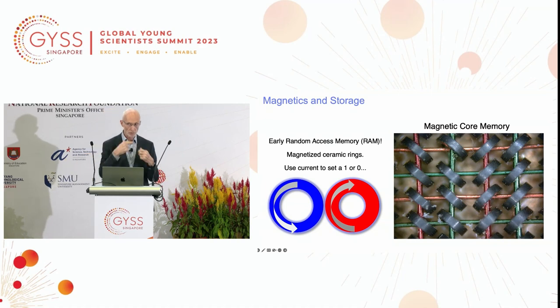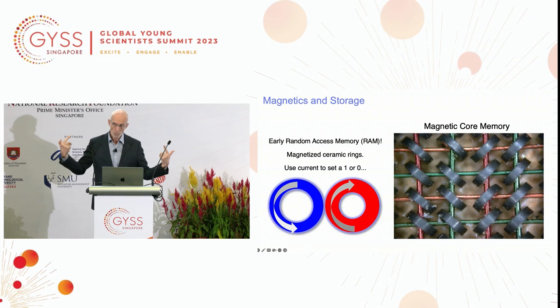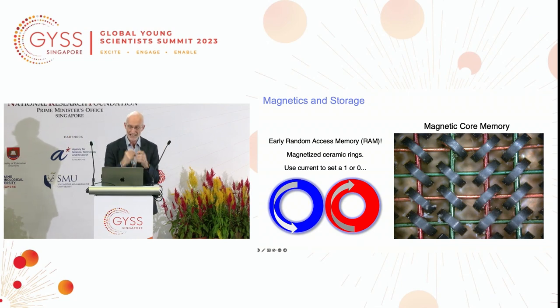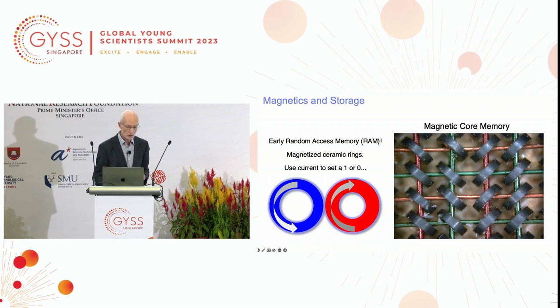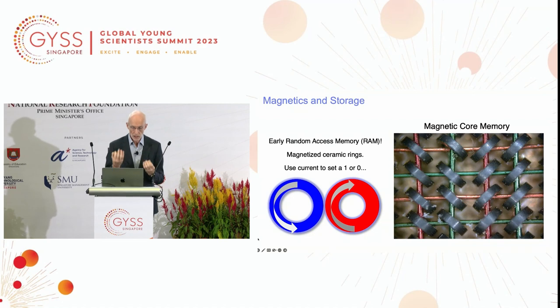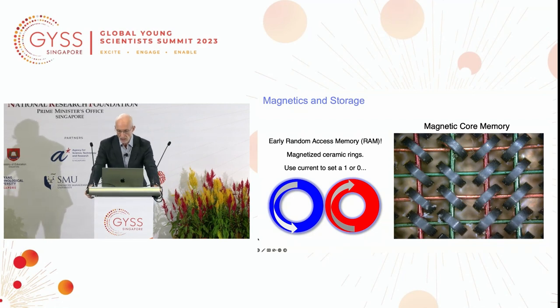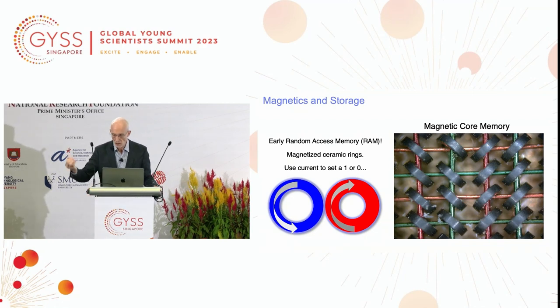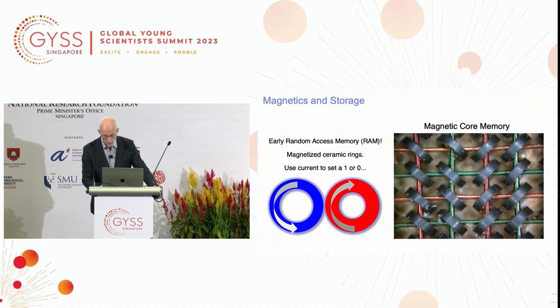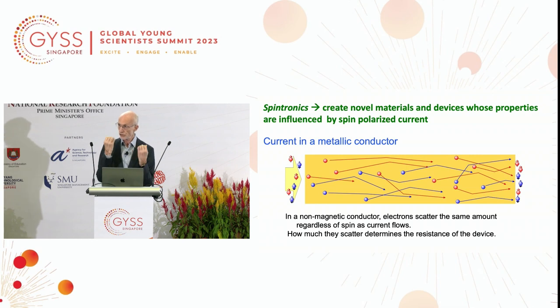If you pass a current through the wire, it will generate a self-amperian magnetic field, and the combination of two fields from two wires at a cross point gives a big enough field that you can change the orientation of the magnetization from clockwise to anticlockwise. This is a very early form of memory, and it has a particular advantage that it's radiation hard, and this is used for space applications for a number of years. But back now to the electron spin.